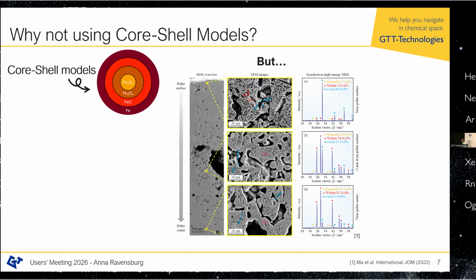And the problem with this model is if you compare it to experimental data, this is one of the papers I like the most. It's from Jan Ma from the Max Planck Institute for Sustainable Metallurgy. And what they did is they took a pellet, they reduced it for 30 minutes, and then they looked at the cross-section, and then they looked at different locations in the pellet and checked what phases are present. And this is plotted on the left side, on the right side. And you see, there are multiple phases present at the same time. So we have in the pellet surface a bit more alpha iron, but also magnetite and wüstite. In the pellet core, in the bottom, we have a bit more magnetite, and then also wüstite and alpha iron.